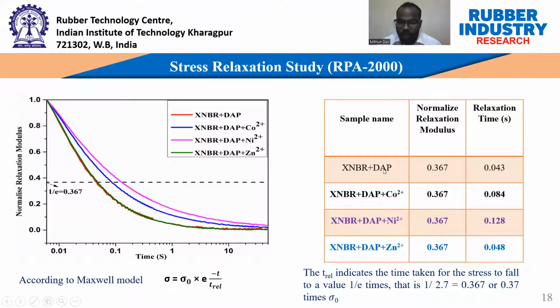In the case of the DAP modified compound alone, the relaxation time at constant modulus is 0.043. For the cobalt containing compound, the relaxation time is 0.084. For nickel, the relaxation time is 0.128, and for zinc, the relaxation time is 0.048. Among these three metal ions, zinc has the lowest relaxation time. That means zinc can form more weak and dynamic coordination bonds compared to cobalt and nickel. Nickel has the highest relaxation time, meaning the highest crosslinking density, which means nickel can form more strong and rigid metal coordination bonds compared to cobalt and zinc.